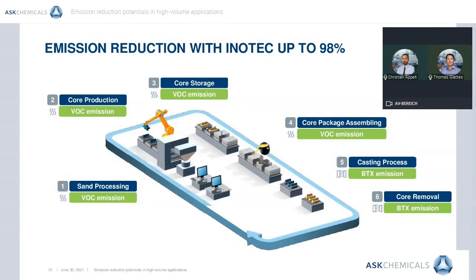Yeah, sure. One question is, what is the current status of inorganic binder systems in iron and steel casting applications? Well, serial applications for Inotec in iron and steel castings in Europe are still missing. We have understood that casting temperatures of 1100 degrees or even higher remain a challenge for inorganic binder systems, as these materials act as a flux for silica sand. ASK has developed water-based coatings for Inotec-bound cores that overcome the sensitivity of inorganic cores towards humidity without core breakage. ASK is currently working with different industry partners with the intention to sharpen the requirement profile for the development. One concept includes, for example, the combination of Inotec forms, so outer forms in the package, and inner cold box cores in sand package procedures in order to reduce emissions and lower the technological requirement profile for the Inotec forms at the same time. Other applications, like iron brake disc productions, rely on the use of 100% Inotec cores that are coated.